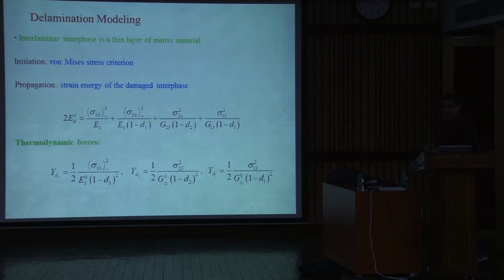So now what is left? Now the failure at the macro level. So that is the delamination. In the delamination, the initiation in this case is given in terms of von Mises stress criteria, because the matrix material is assumed to be isotropic in nature. So I can apply von Mises stress criteria.